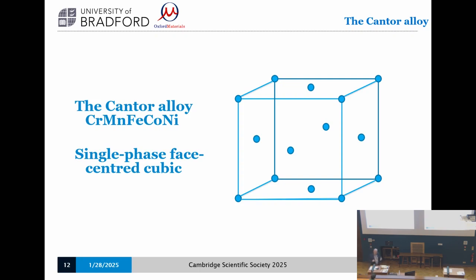So the typical thing that happens when you start alloying is you can get a little bit of replacement on the crystal structure, but once you start adding any amount of alloying element, or certainly if you add lots of different ones, you start to form compounds. Because when you mix different stuff up together, we know that they form compounds. That's what chemistry is all about. Now, this material, which we discovered in the middle of our 20-component material, consists of a face-centered cubic structure with a random arrangement of 20% of chromium, manganese, iron, cobalt, and nickel atoms randomly distributed onto this. Nobody could have predicted that. Nobody did predict it. It was entirely a surprise.